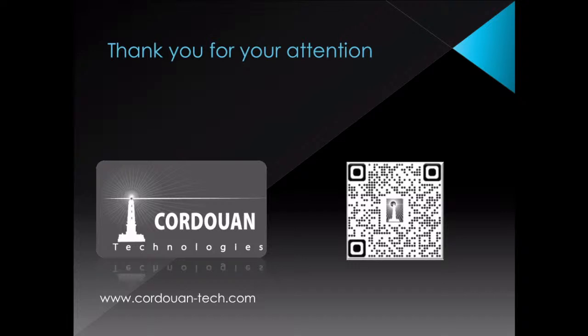We used to say that from 1 nanometer to 10 microns, it's okay. More or less, I prefer to say from 1 nanometer to 1 micron. Because from 1 micron to 10 microns, first, yeah, this is not so interesting. You have all the ways to measure, you make the measurement. And after 1 micron, it depends really on the density of the material that you're using.